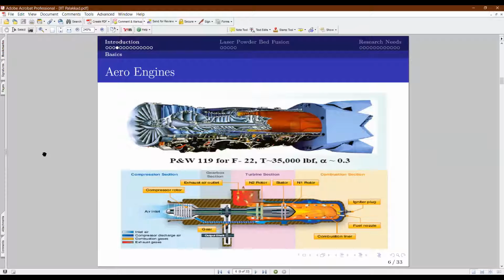Any component developed for the aero engine has an acceptance rate of somewhere around 30 to 40%, because of the stringent NDT requirements and the tolerable defect limit. At the same time, there are higher property requirements, especially high temperature properties and dynamic property requirements. Components either fail in the testing stage or in the NDT stage. So the acceptance rate comes closer to 30 to 40%.